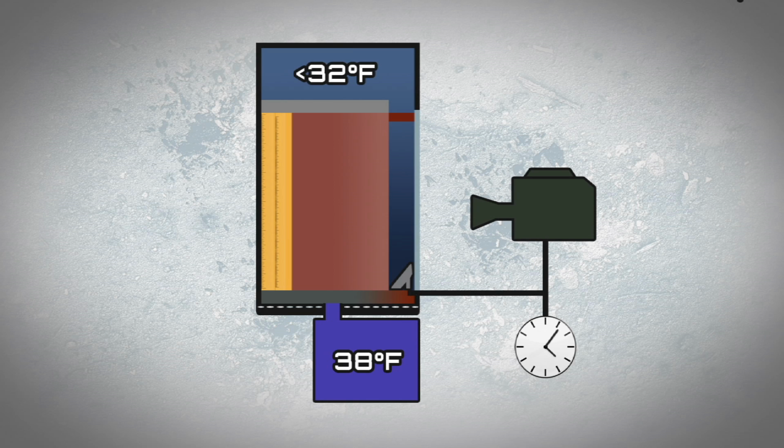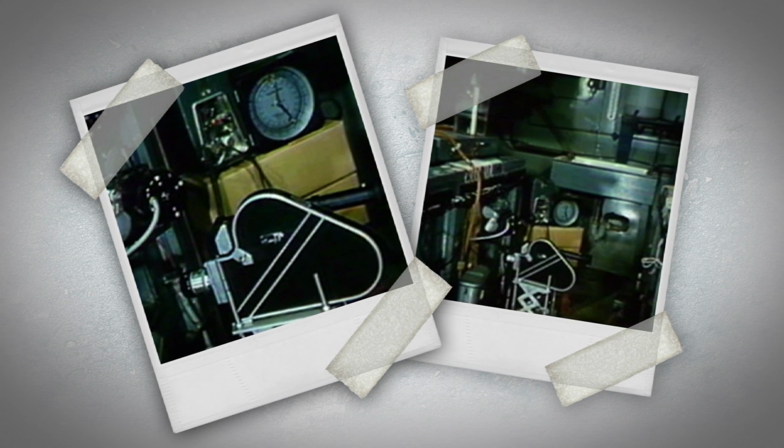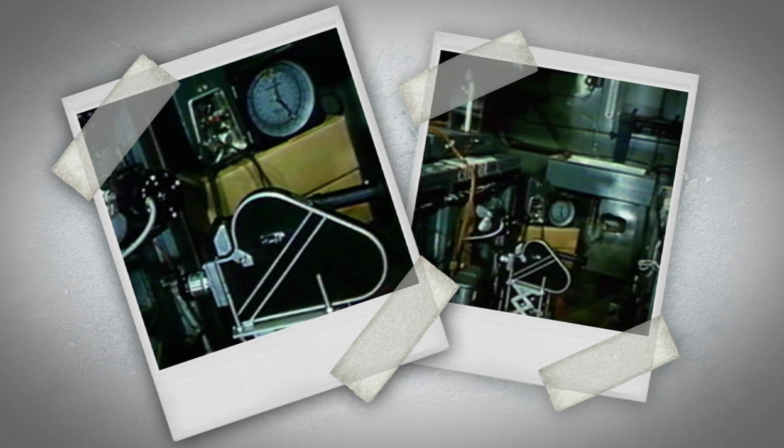The temperature was controlled so the soil sample would freeze at a slow rate, about 1/4 of an inch in depth per day. A time-lapse camera captured an image once every 4 minutes. Here's the resulting film. When speeded up, the activity of several weeks is compressed into a few minutes. 1 second on the watch equals about 1½ hours of real time.